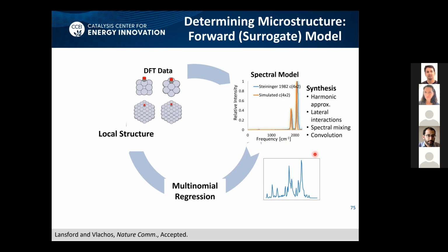So here you see, after a few thousand of the spectra we generate on the computer, we create synthetic data, which does a convolution of the spectra. And then I use basically two neural nets, one for the type of site, and one for the plane, and I can start getting structures back. So in this piece here, we do the inverse modeling, right? We forward DFT data to predict spectra, we learn the spectra, and then given experimental spectra, predict the structure.